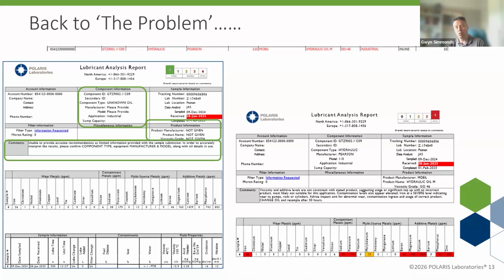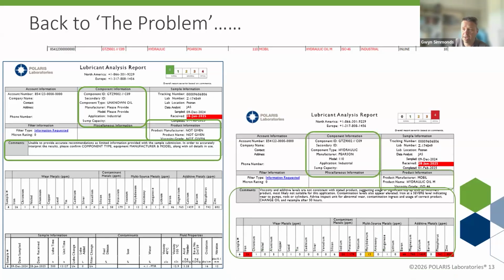If we look at the same report, now the customer has provided us with that vital information, we know it's a hydraulic. We know the manufacturer, the model, and they've confirmed the product in use as well. We can now make a much more informed interpretation and recommendations just based on that additional information they've provided. And you can see here that a lot of the data is flagged. So there's relatively high levels of iron, there's levels of contamination, and it's clear to see that the additive package in this particular sample is very different to what we'd expect in this hydraulic oil.